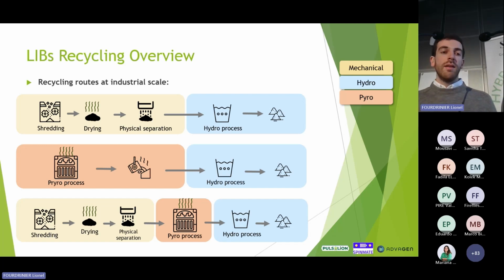Then we have the pyrometallurgical process plus hydrometallurgical process. So in the pyrometallurgical process, the batteries are smelted, and it results in 2 different streams: one alloy that contains all the valuable metals, and the slag that contains the lithium. So then in the hydrometallurgical process, you can recover the valuable metals from the alloy and the lithium from the slag. The good thing about this process is that you can have pure materials at the end, because you don't have the cross-contamination that you have in the mechanical pre-processing. But the main problem is that you also lose some materials because you burn all the organics during the smelting. So you cannot recover the liquid electrolyte, for instance.